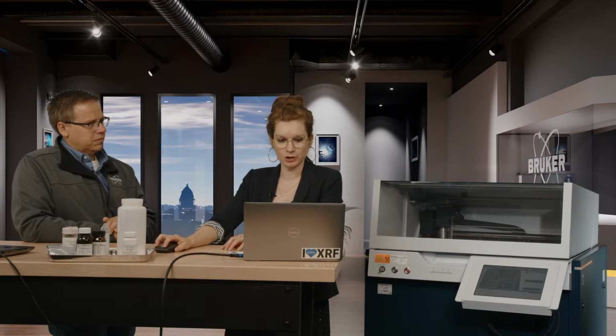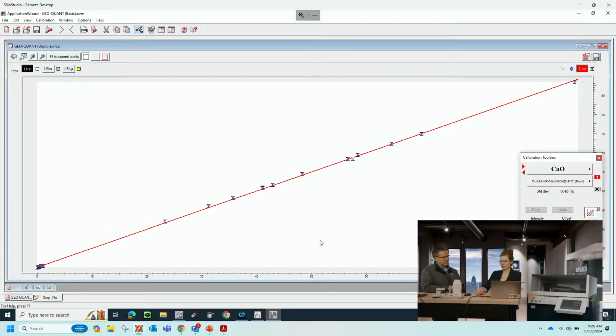So if I want to show you an application, it's already open, right? Then you measure your samples against the concentration, and then you can plot the intensity, and then you get these really nice curves. And when I get an unknown, it's measured, it registers, I don't know, an intensity up here, compares it to my calibration curve, and it knows, hey, I have 80% calcium oxide in there.